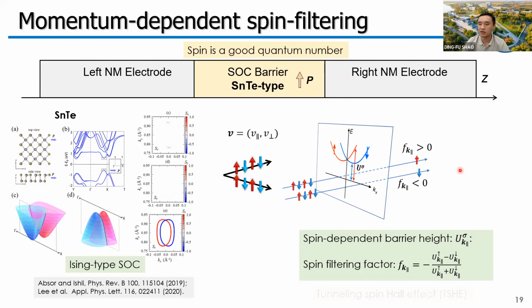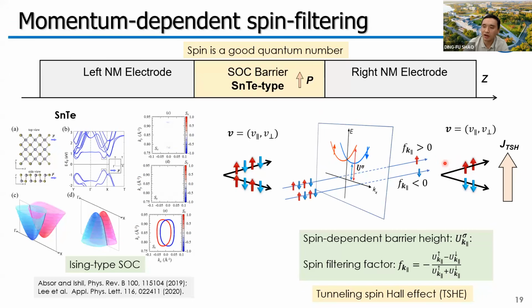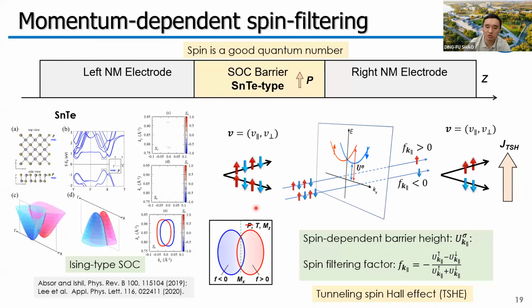As a result, after tunneling, we find that half of the spin up electrons are filtered out, and for the remaining electrons, the spin up electrons majorly have positive transverse velocity, and the spin down electrons majorly have negative transverse velocity. This generates a net transverse spin current. This effect is called the tunneling spin Hall effect. Here, we only show the distribution of the spin filtering factor F along the kx direction, but in tin telluride, the distribution of F in the 2D Brillouin zone should look like this.